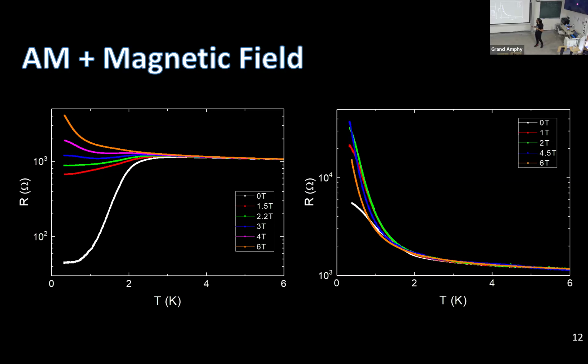At 4.5 Tesla, we see it even clearer. And thus, again, in the same cool down, the same measurement, nothing changes. Once we see this metallic phase and we add magnetic field, it disappears. So we don't believe this is adding noise to our sample. It doesn't mean that we don't cool down the sample. We can reach the temperature.